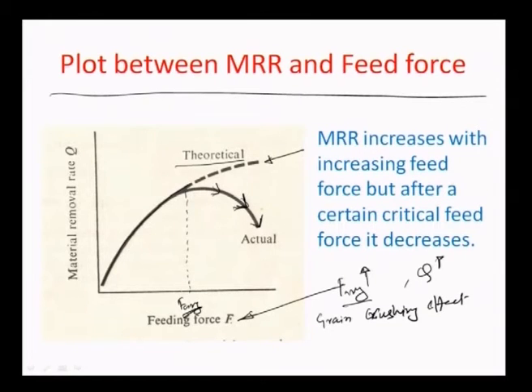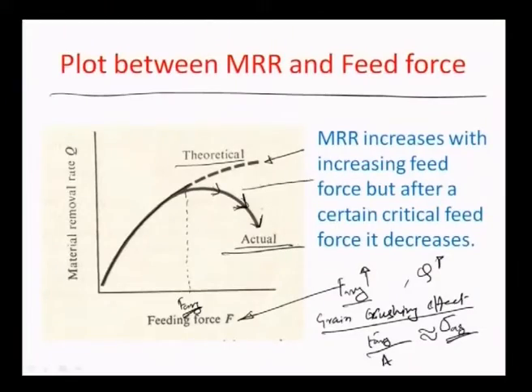So if the feed force is higher and higher, to a value where this F average per unit area of the grain equals the ultimate flow stress of the abrasive grain itself, then there is a possibility that the grain itself would get broken into pieces, and there is a crushing effect. So the number of active grains available at that critical feed force would simply go down, because they are themselves getting crushed. It is therefore reasonable to assume that because of this crushing effect, the number of available complete grains which come between, let us say, the tool head and the workpiece is lessened, and so would be the material removal rate. Therefore the actual trend of the material removal rate is shown by this particular illustration.